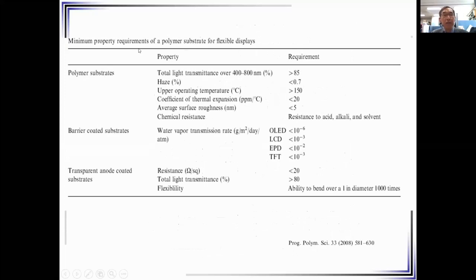Here I summarize the minimum property requirements of a polymer substrate to be used for flexible display. If we use polymers for a practical or commercial monitor or display, maybe these properties should be higher or better than this requirement. But at least if you develop at university or laboratory scale, the basic requirement is a property like this. For example, the polymer should be transparent, with at least 85% transparency. And they should maintain operation at temperatures over 150 centigrade. As I told you, PET, polyethylene terephthalate, is an excellent transparent material, but the Tg is around 80 degrees, so it cannot be used for a flexible substrate. Demonstration is okay, but not from a practical point of view.